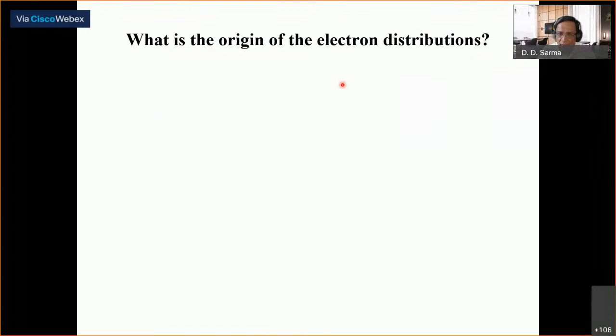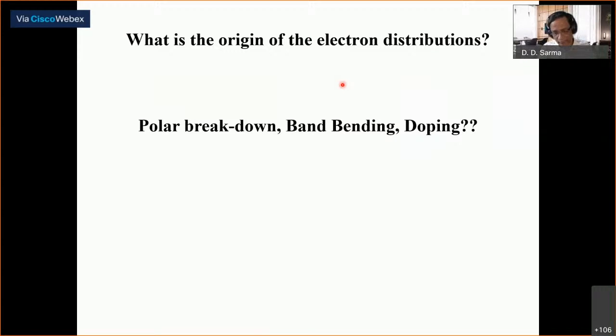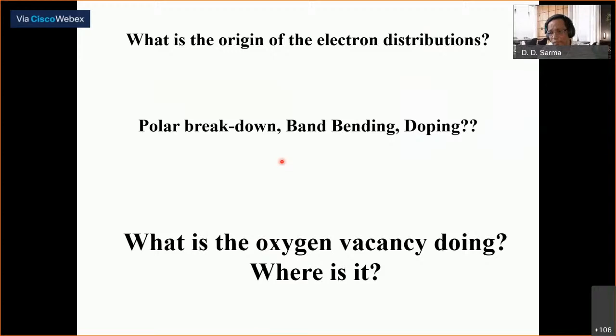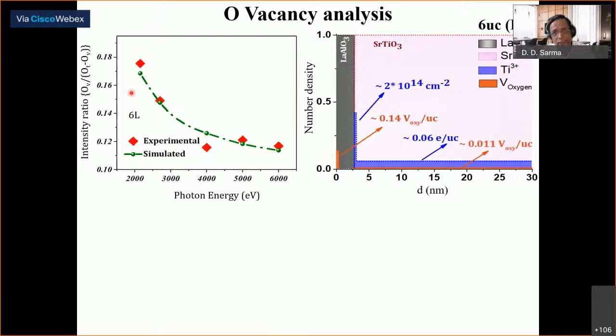But what is the origin of this electron distribution? Of course, there are many kinds of expectations, many theories and many scenarios have been discussed. What I'm going to talk about is oxygen vacancy, because it turns out that you have a spectroscopic signature of oxygen vacancy, and we can map out how the oxygen vacancy is distributed. There are very good reasons to expect that oxygen vacancy may play an important role, from the physics of strontium titanate that we have known for many years, as well as from the fact that how these samples behave depends critically on how they're annealed in oxygen atmospheres. Now, I'm not showing you the experimental result, but directly telling you how the oxygen vacancy signature varies experimentally. Those are these red data points. And again, the simulated data that fits the distribution well is given by the green.